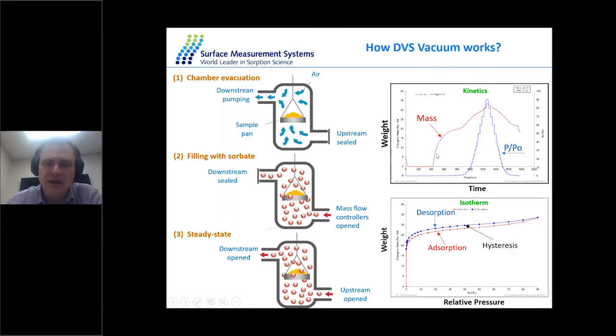Because the adsorption process is quite slow, in this stage we are just waiting for mass equilibrium. Mass equilibrium is defined by the flatness of this line. In our case, we use a mass equilibrium criterion called DMDT. We typically set DMDT to, let's say, 0.003% per minute for a duration of 10 minutes. This means that when the threshold value is met, the software moves automatically to the next stage. When it does, the partial pressure increases, and again we wait for the mass equilibrium criterion.